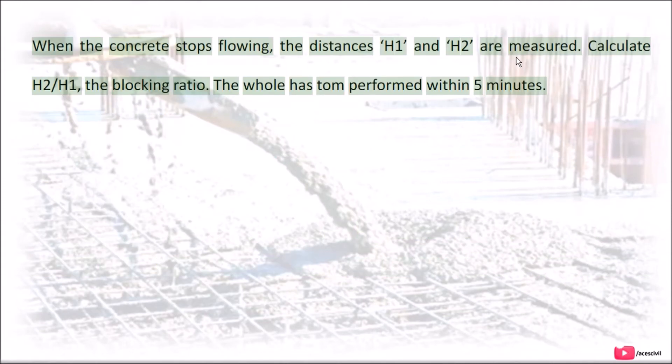When the concrete stops flowing, the distances H1 and H2 are measured. Calculate H2/H1, the blocking ratio.